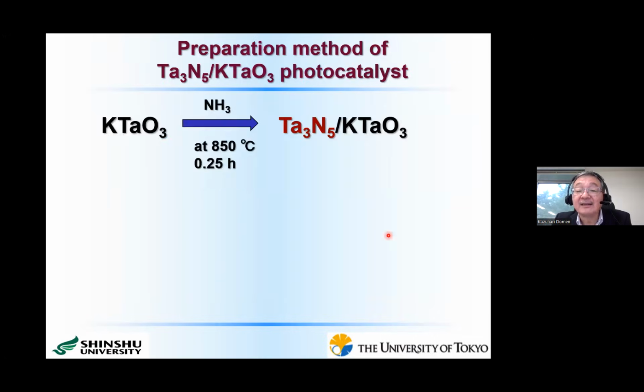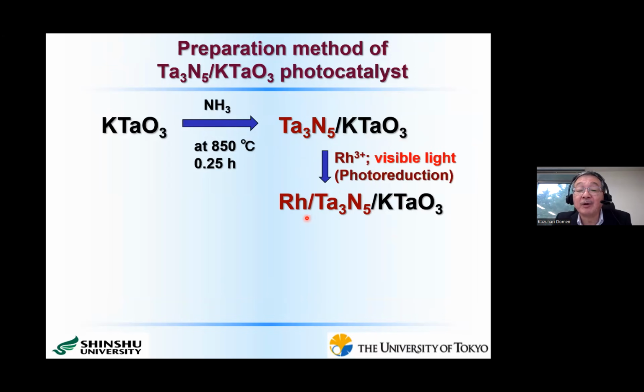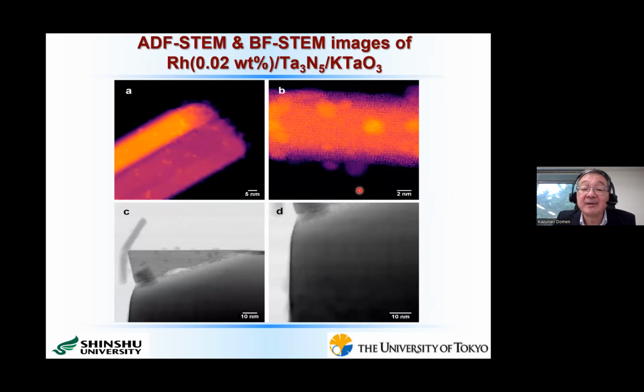So we decided to use this Ta3N5 particle prepared on the potassium tantalate to prepare our photocatalyst for the water splitting reaction. In this case, again, we deposit metallic rhodium nanoparticles at first. But in this case, we use only visible light to excite only this Ta3N5, so as to deposit the metallic rhodium nanoparticles only onto the Ta3N5 nanorod. Here I show the STEM image after metallic rhodium nanoparticle deposition. I hope that you can see these small particles. This is a 2 nanometer scale bar, so they are 2 to 3 nanometer particles.